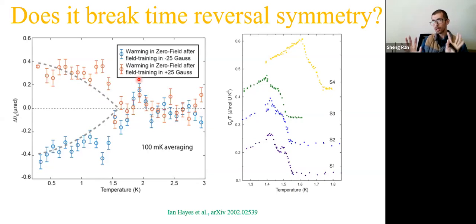Then people were a little bit confused at the beginning because this is really an orthorhombic system, so all the irreducible representations are one-dimensional. You're not supposed to have time reversal symmetry breaking. Like strontium ruthenate is a tetragonal system, then you can have px plus ipy. But here is an orthorhombic system.